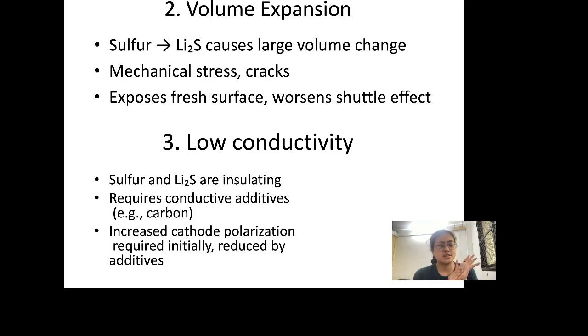But the crux of this is that elemental sulfur and lithium sulfide have a huge difference in density, and that means that the volume they require is very different, which means as and when the redox reactions happen, there is an expansion and a contraction that happens at the cathode side, and there is a huge mechanical stress applied to the cathode side. This is going to lead to failure and mechanical stresses, which lead to probably lattice deformations, which could affect intercalation, or it could lead to cracks.